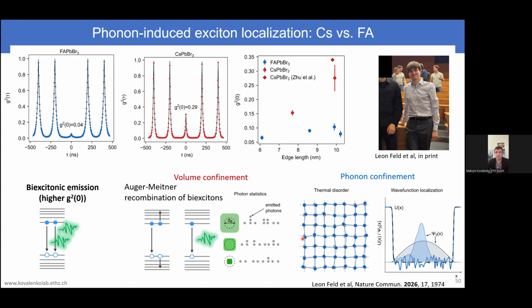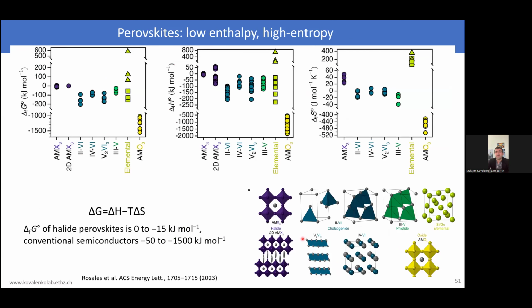So these materials are inherently highly entropic. There is a lot of motion. Moreover, I briefly show this paper also. Moreover, this is reflected in the entropic contribution to their free energy formation. So the entropy here is actually way higher than for any more rigid semiconductor. And that is actually probably the reason these lattices even exist.